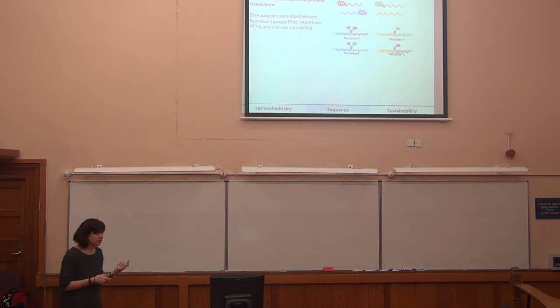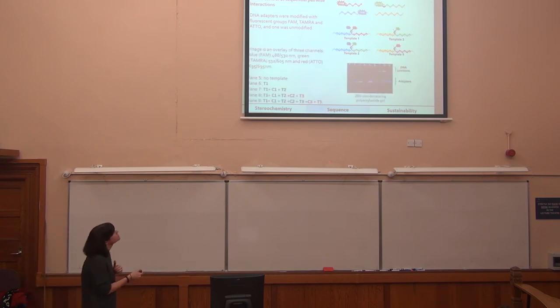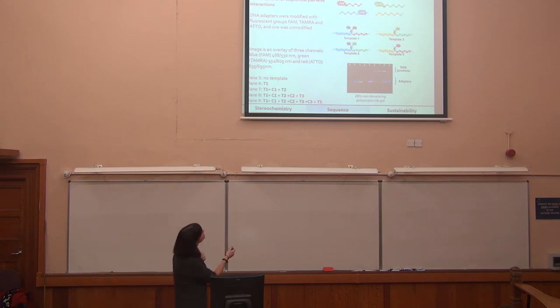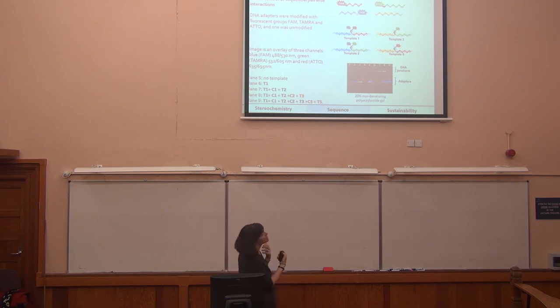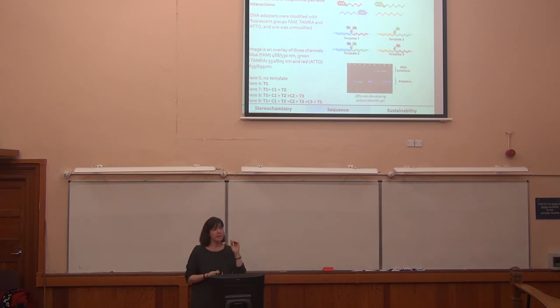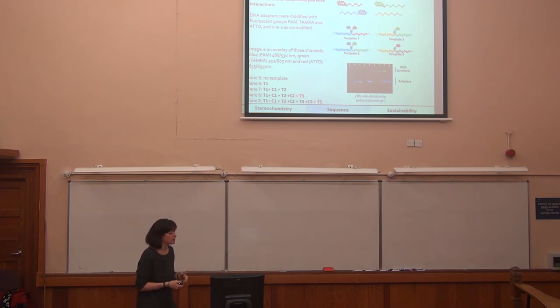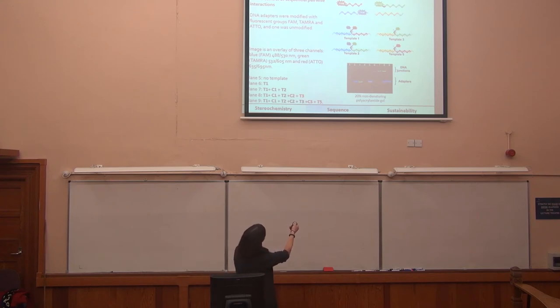So we looked at whether we could do this in a simple gel experiment, and just to walk you through, 1 to 4 are the initial strands, so the FAM, TAMRA and ATTO, you can't see the yellow one since it has no dye on it, but 5 is the adapter mixture, all four adapters together, so you see a mixture of them all, you can't really see the green one, obviously. But then when we add in 6, T1, which is template 1, which says please bring blue and red together, which makes purple, you can see our purple band, and you can see the green has been left behind. We can wipe that instruction and then add a new instruction, T2, which says bring blue and green together, and you can see the blue-green band and the red left behind.